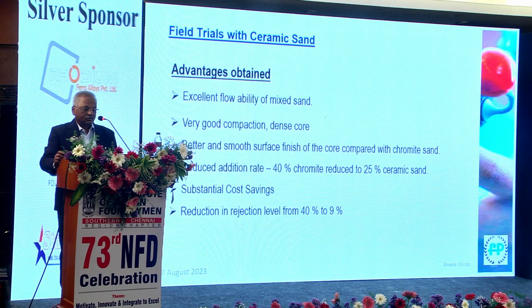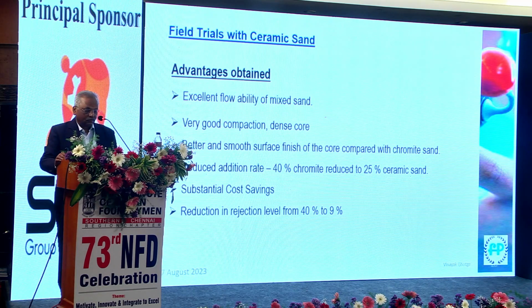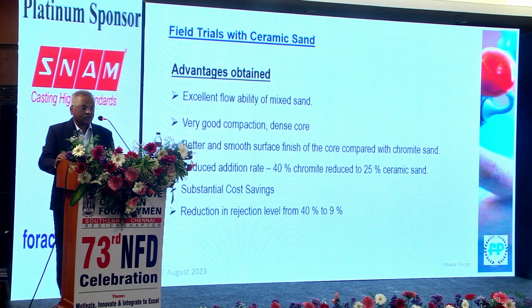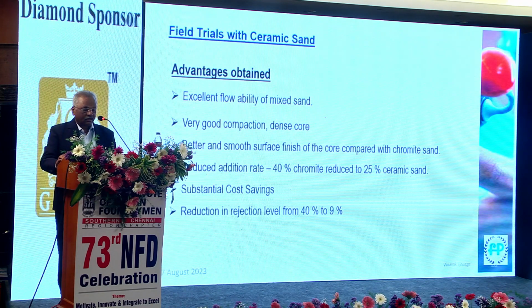The advantages foundries get with ceramic sand is excellent flowability of the mixed sand, very good compaction, dense core, better smooth surface finish of the core compared with chromite sand, and reduced addition: from 40% chromite, they could come down to 25% of ceramic sand. So there was a cost saving also involved, and the rejection was also controlled from almost 40% to 9%.